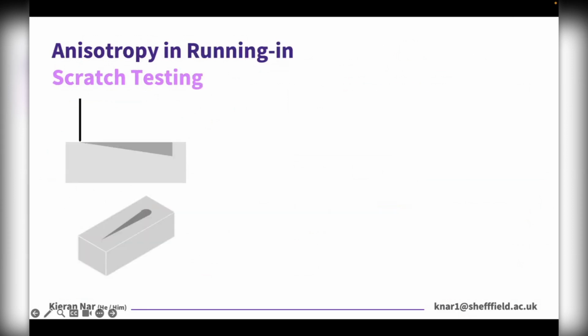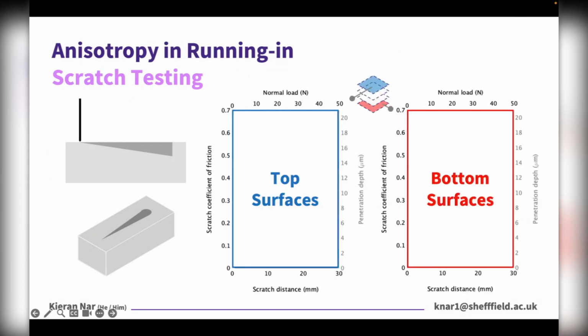And this was also confirmed via some scratch testing analysis we did, and this involved scratching different nylon 12 top and bottom surfaces, but instead of applying a constant normal load, we instead applied a progressive load from 0 to 50 newtons, just like so. And this animation shows the data collected during each scratch.